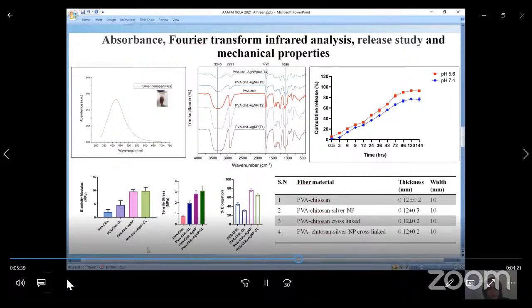Just to confirm the mechanical strength of the fibers which we obtained, we have seen that the elasticity modulus, tensile strength, as well as percentage elongation were found to be quite good with respect to the cross-linked fiber, and also on addition of silver nanoparticles, we have seen that there is good mechanical strength.